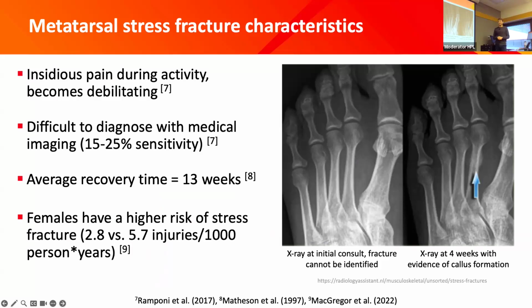On top of that, they're pretty difficult to diagnose. So here are some images of a stress fracture of the second metatarsal, so this bone here. The first image on the left is an X-ray at the initial consult. I'm not an X-ray tech, but I cannot see any kind of fracture there. The second image is 4 weeks later, and the only evidence of stress fracture is this slight callus formation. So the bone's actually healing, and that's what we're seeing. We don't actually see the crack itself.